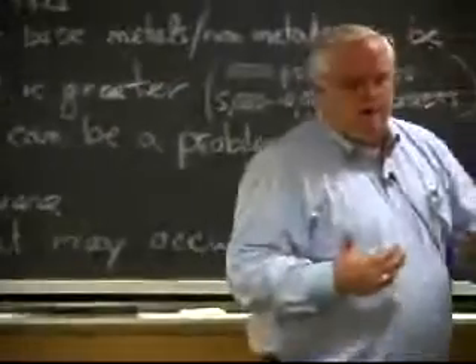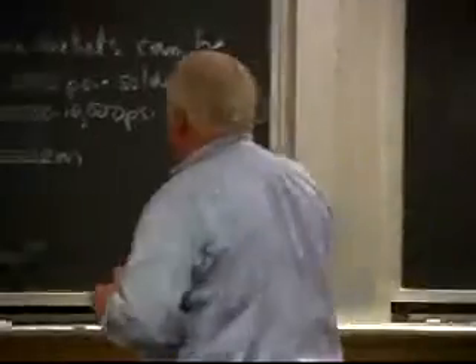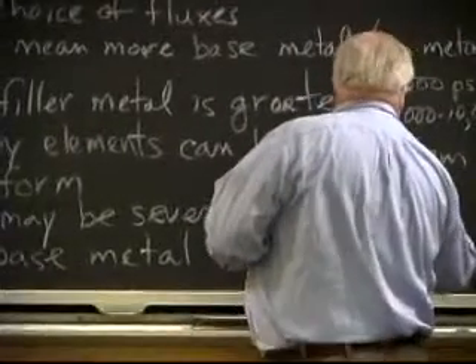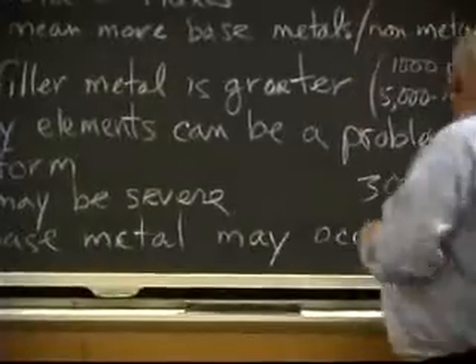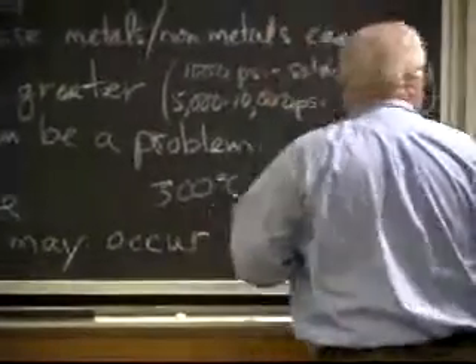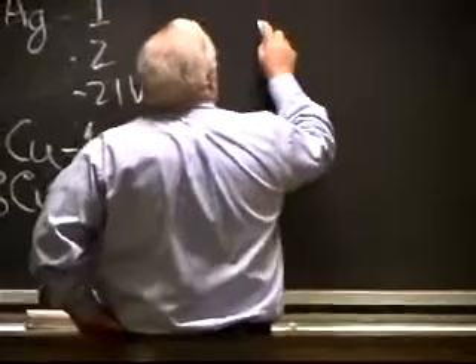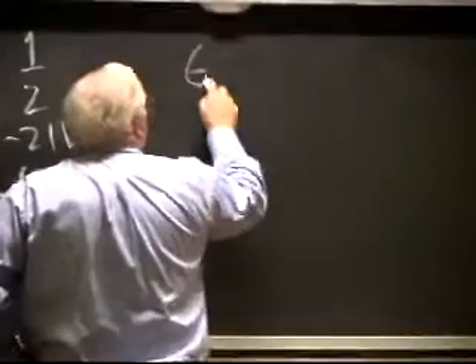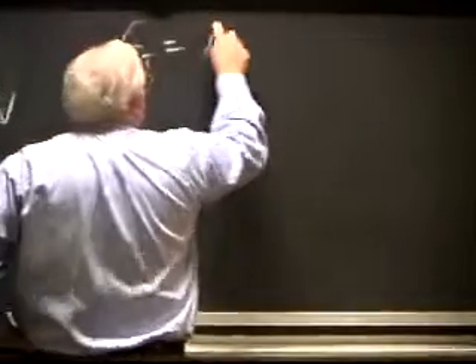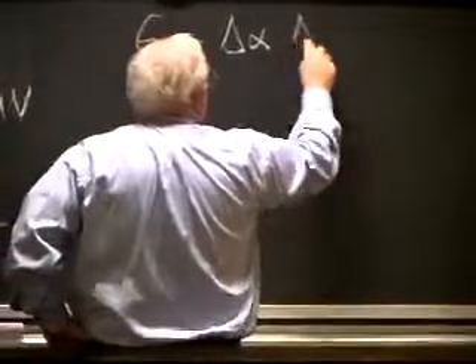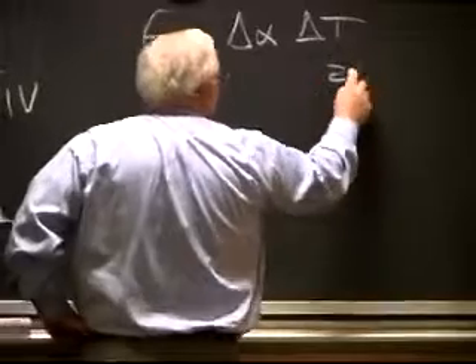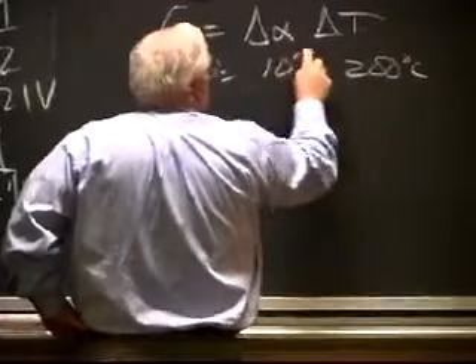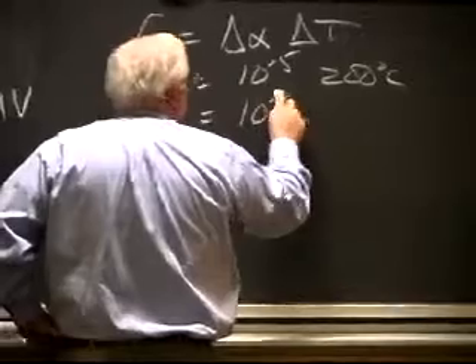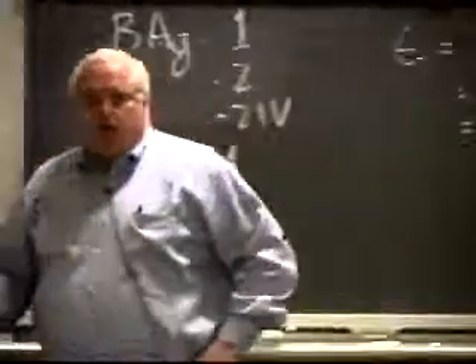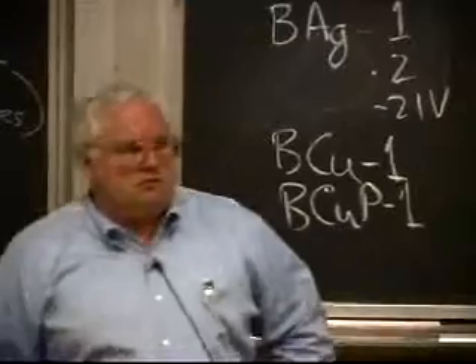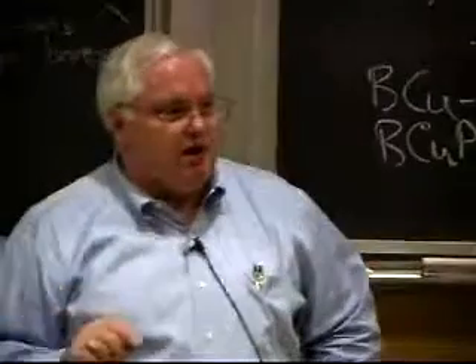Thermal stresses can be severe. We've talked before about the fact that 300 degrees centigrade is all you need to reach yield level residual stresses in most things. Well, actually, I did it once before. The thermal strain is equal to the difference in thermal expansion between two materials times the difference in temperature. If this is 200 degrees centigrade and this is 10 to the minus 5, the thermal strain is 10 to the minus 3. 10 to the minus 3 is 0.002. That's the yield strain for most metals. Okay, 0.2% offset is 0.002.